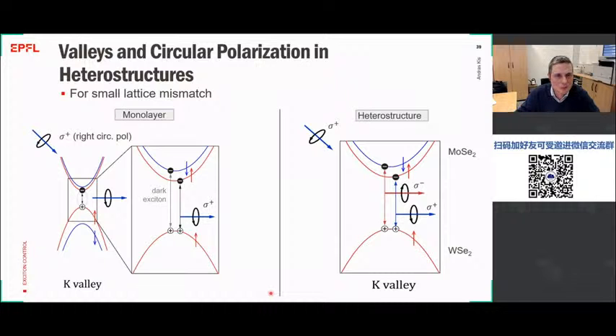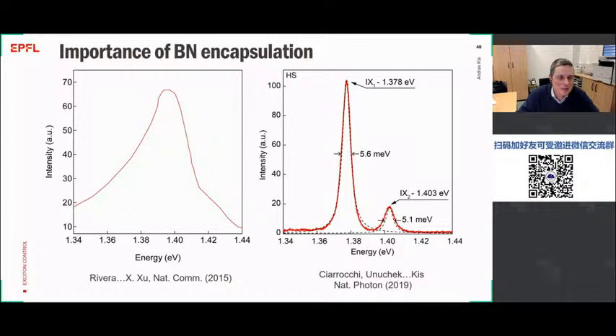In heterostructures, you actually have a more complicated picture. With the circularly polarized light that you shine on the structure, you select a certain valley. But now in this valley, in the heterostructure, you can have both spin triplet and singlet transitions, and these will then give rise to emission of light with different polarizations. And you can actually change electrically which polarizations you're getting and which regions of the heterostructure are active. Now, to observe these two peaks, it was important to encapsulate the materials in boron nitride. This was the first example of interlayer exciton observed in these heterostructures, but in that case, they were not using encapsulation, so they were not able to resolve the finer features in the spectra. But with the boron nitride encapsulation, we could really resolve these two peaks, which corresponded to these singlet and triplet transitions.